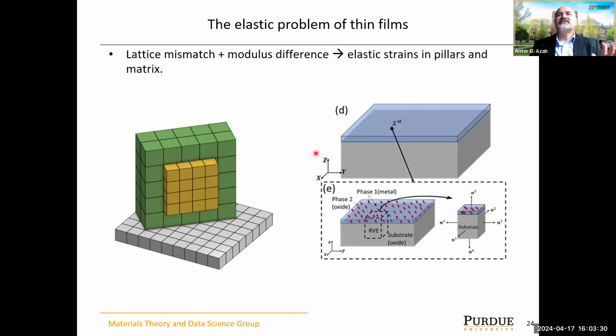In order to answer this question, we need to do two things. Number one is to capture the strains. And number two is to capture the strain effects on the kinetics by looking at how the strain impacts the hopping energies and binding energies on the surface, because the combination of those two energies contribute to the hopping rates on the surface. So there is an elastic problem to solve, and then a reparameterization of the energetics on the surface as a function of the strain state at the surface itself.